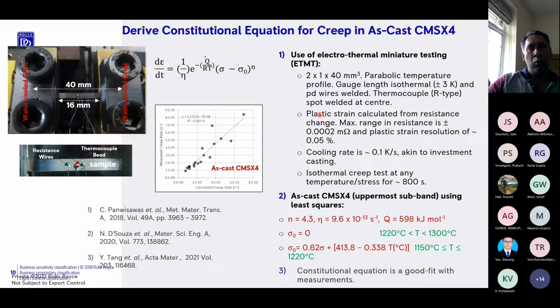In this miniature testing method, you do not measure the plastic strain using extensometry, because clearly you cannot pin an extensometer on such very thin cross sections. Rather, you measure the plastic strain indirectly through resistance, because as the material plastically strains, either in tension or compression, the resistance changes, and therefore by using the resistance, you can calculate the plastic strain. So clearly we do not have extensometry in these experiments.